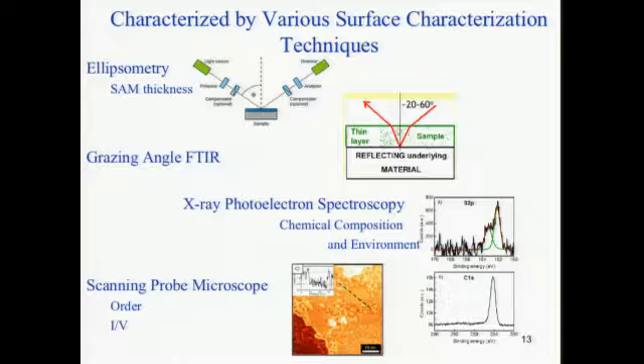There's a good number of characterization techniques that are involved in actually showing that you have a monolayer. Ellipsometry, which is a relative method because it's using a difference in refractive index when you're looking for thickness. You start off with your substrate that you haven't modified. You get the refractive index of it. You modify it. The refractive index is going to change, so how it interacts with the polarized light is going to be different, and that difference can be spit out using Snell's law to give you a thickness, and so forth.